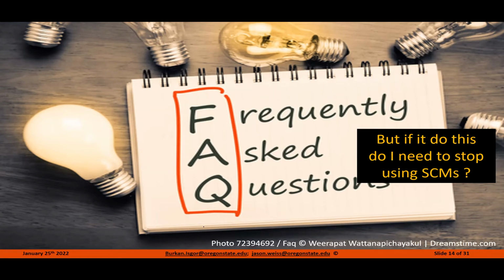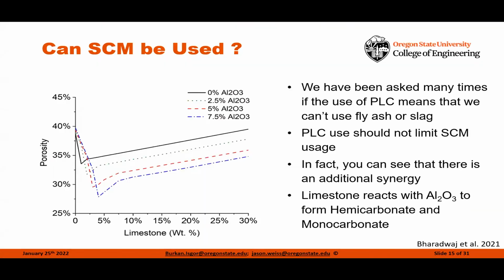And right now we believe that there's 49 out of the 50 states that are permitting the use of a C595 cement. We're seeing a lot of transition over to this. And what we can say is, if your SCMs are silica based, you're essentially going to see the same type of performance. However, if your SCMs have alumina in them, what you're going to notice, especially as we start increasing the amount of reactive alumina in these systems, is a further decrease in the porosity of the system, a further stabilization of some of those phases.